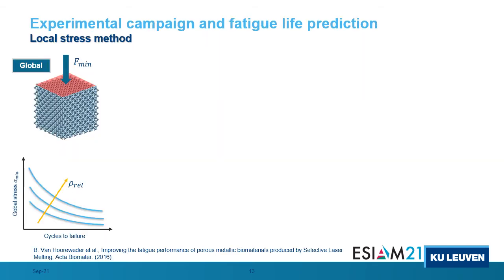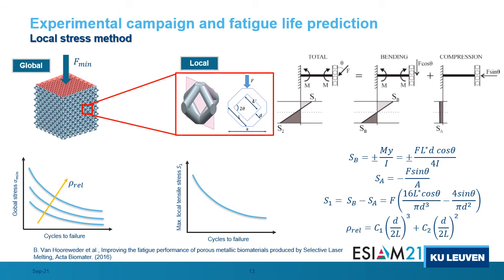In order to clarify the concept of local SN curve, it is important to introduce the local stress method. When we look at fatigue performances of metal lattice structures, we can do it from two different points of view. The global point of view treats stresses as a ratio between the forces and the cross-section of the coupons. Given the same global stress, the more the material, the higher the fatigue resistance. Therefore, SN curves are strictly related to the coupon's relative density. But if we look locally, the external compressive stresses generate local bending and compression stresses along each strut. The strut, in this case, can be seen as a clamped beam subjected to an inclined force that generates tensile and compressive stresses across the strut's cross-section. For fatigue problems, the local tensile stresses can be considered as the main driving factor for fatigue crack initiation.